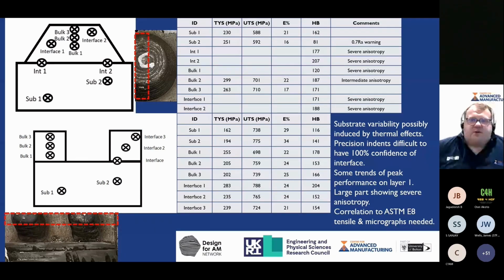The precision indents that we are proposing we took, we don't have 100% confidence, but we are relatively confident that they were indicative of those areas. There certainly seems to be a bit of a trend showing that peak performance was maybe at layer one, but it gave us some food for thought in terms of WAM and the potential that we should increase this study to make sure we get these full Z height coupons, the ASTM-E8 standard tensiles and micrograph performance, as you would expect in any industrial sense, and then keep looking at the PIP versus tensile debate in these parts.